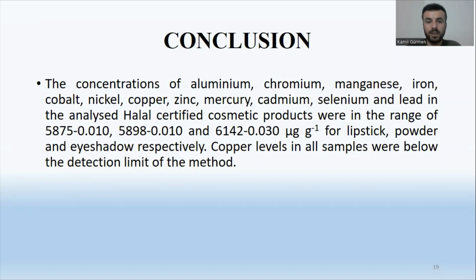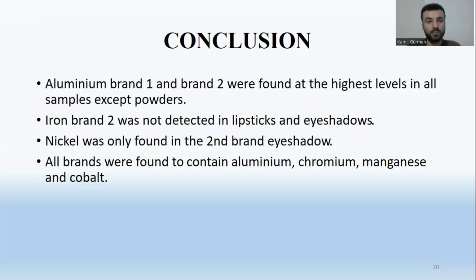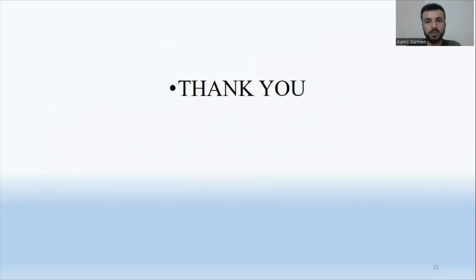Copper levels in all samples were below the detection limit of the method. Aluminum in brand 1 and brand 2 was found at the highest levels in all samples except powders. Iron in brand 2 was not detected in lipstick and eyeshadows. Nickel was only found in the brand 2 eyeshadow. All brands were found to contain aluminum, chromium, manganese, and cobalt. Thanks for listening.